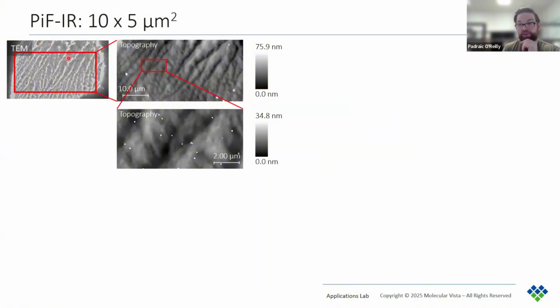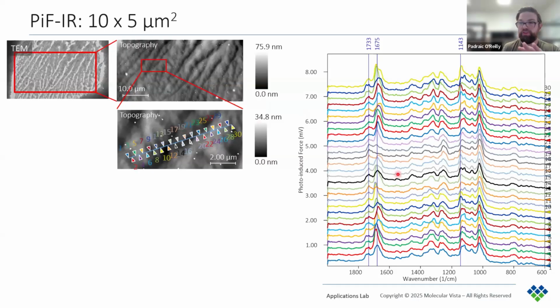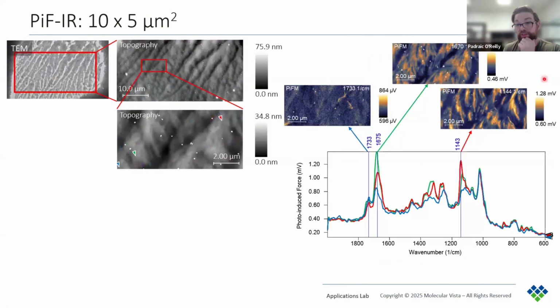So as we zoom in on this crystallized region to a 10 by 5 micron section, then we took spectra in sort of a line across it. Now, there are a lot of spectra here, so the variations might not be immediately obvious, but they were primarily around 1730, 1670, and 1140. Now, if we just look at a few of these spectra, you can see this more clearly. So around 1730, the change here is very subtle. So the blue spectrum here is slightly taller. But we can clearly see the peaks around 1670 and 1140 increase for the green and red spectra, respectively.